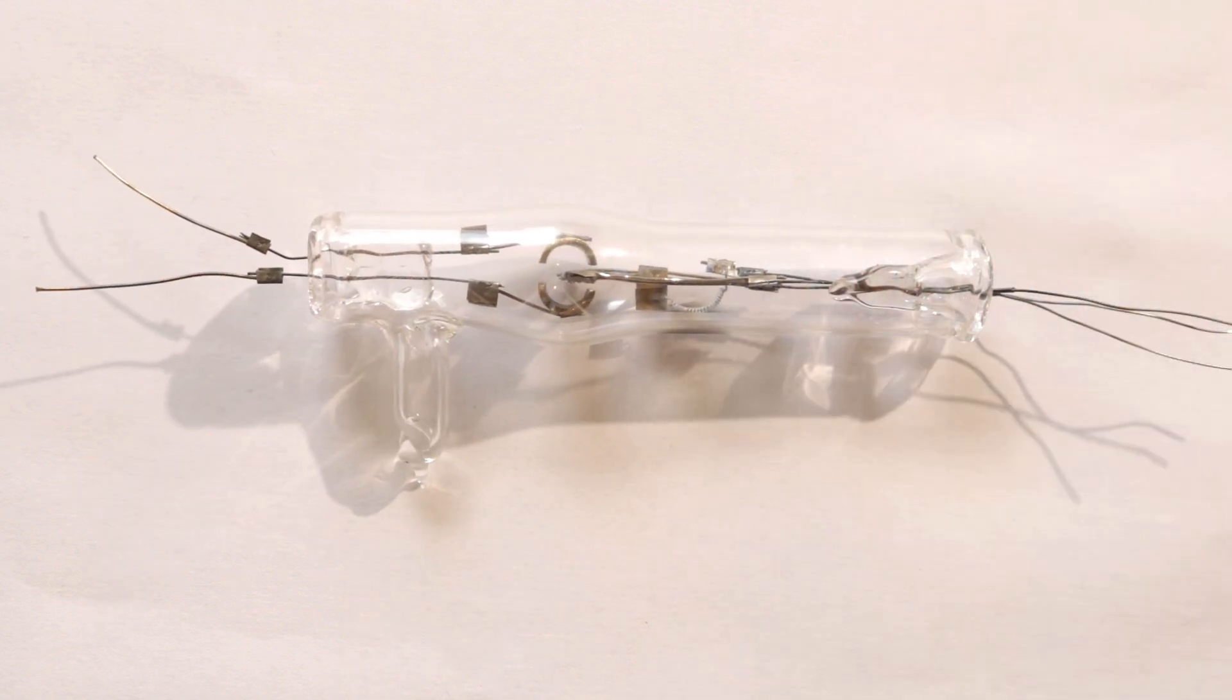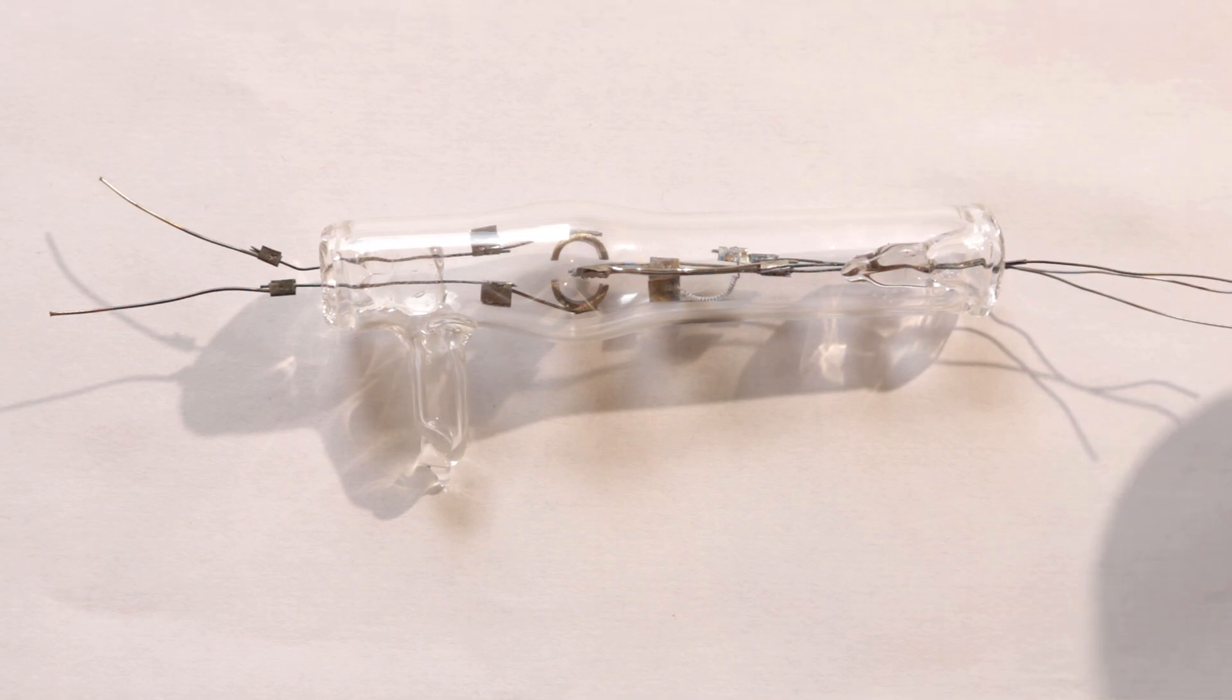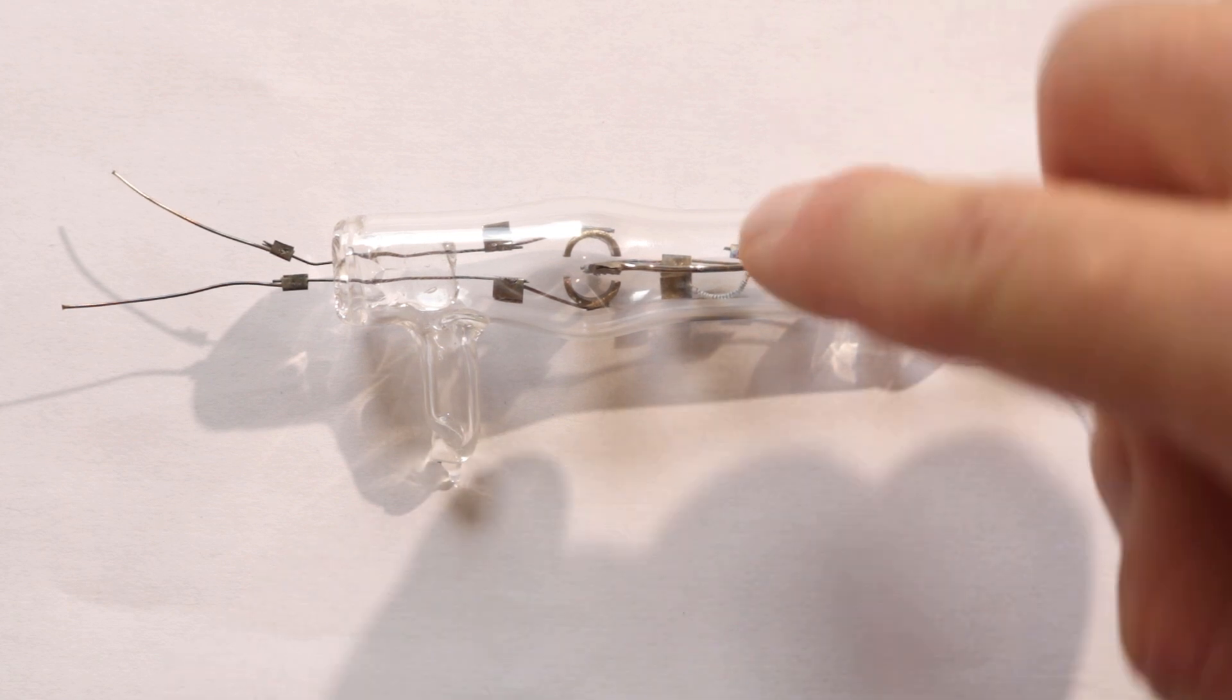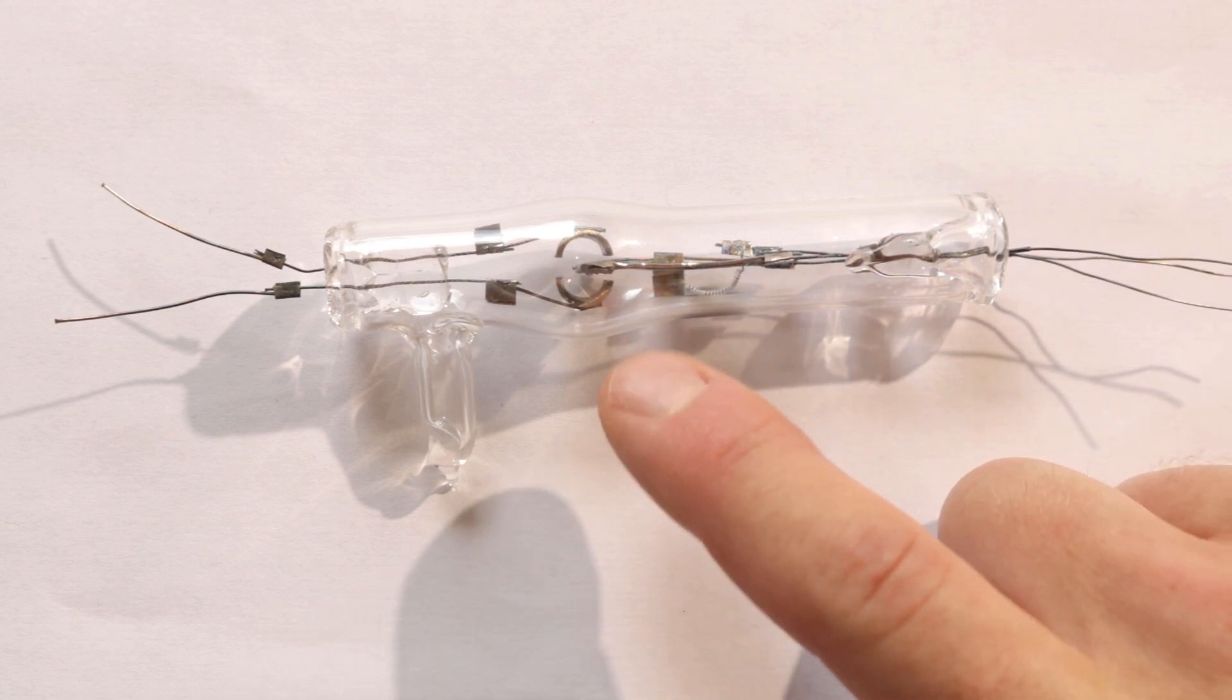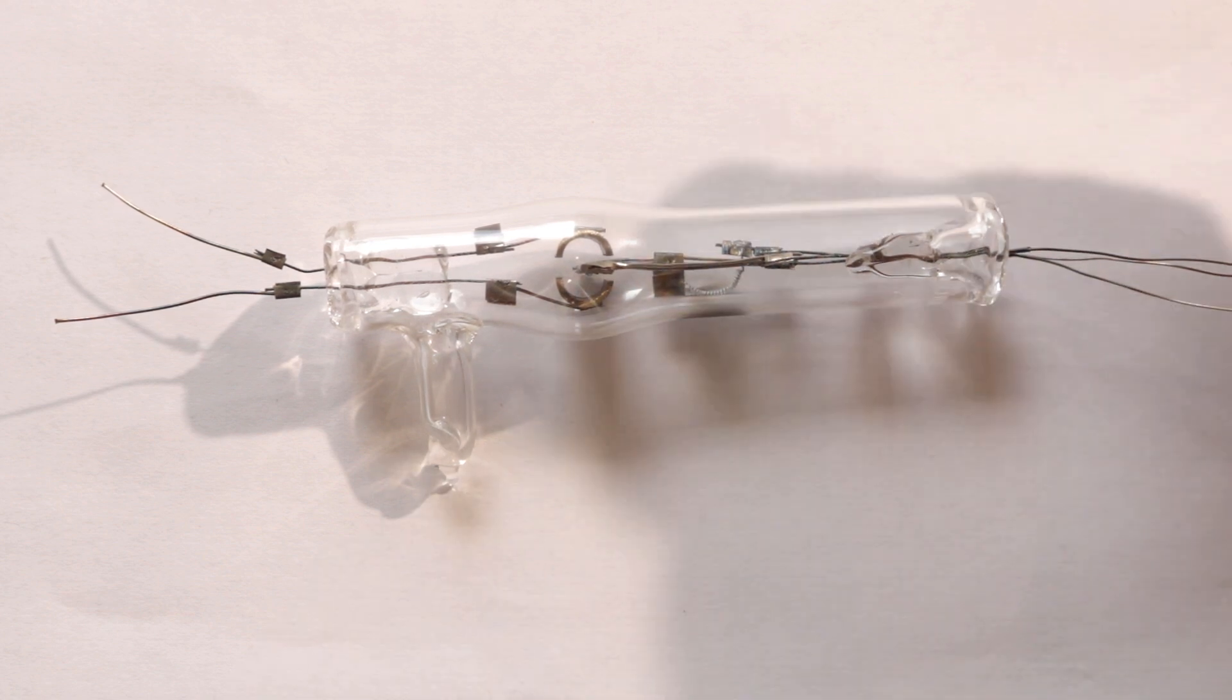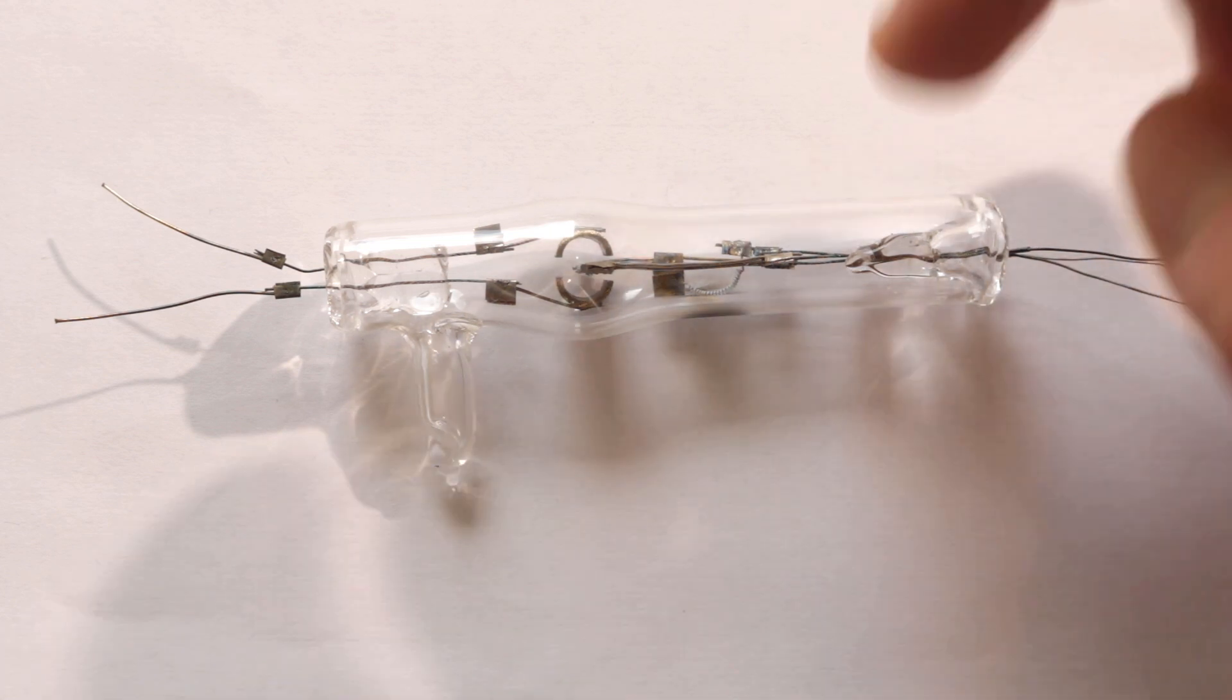I don't know how complicated it will be to get this to work if I keep vacuum in a tube like this, but we will see. What I also tried is coating the cathode, so the filament, with some barium. So if you coat this in barium nitrate and decompose it by heating this in the vacuum, it will turn into barium oxide, and this will cause the so-called work function to be lower. It will cause to emit more electrons out of this cathode at a lower temperature. That's obviously very good because then you don't have to heat up the filament that hot to get enough emission current, and this will be very good for the longevity and the lifetime of the tube.